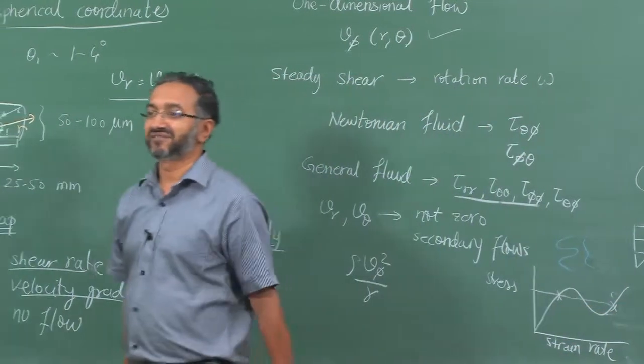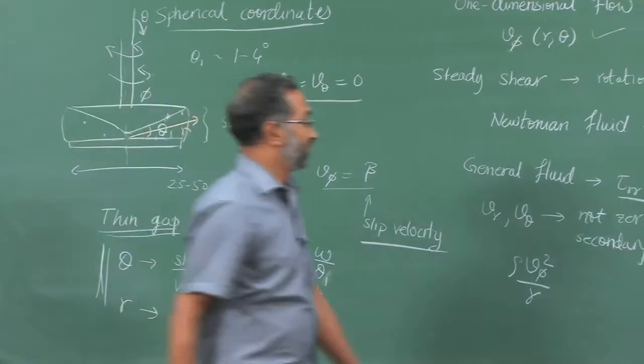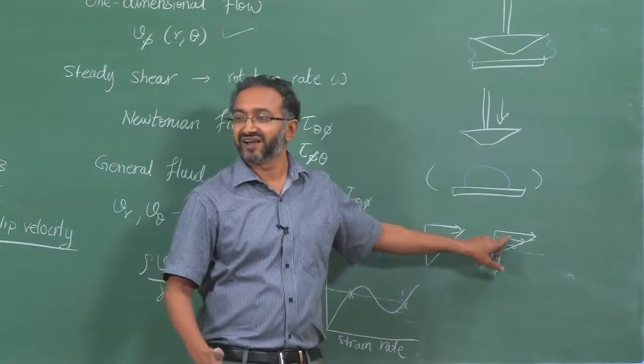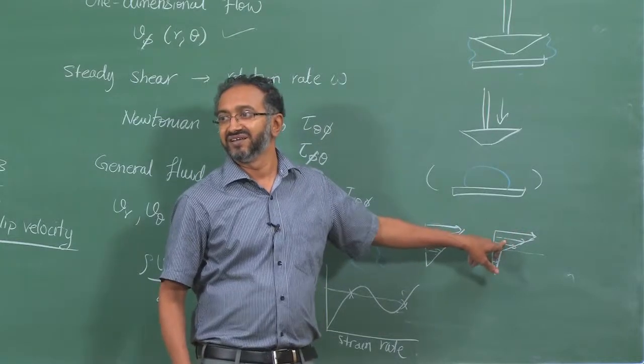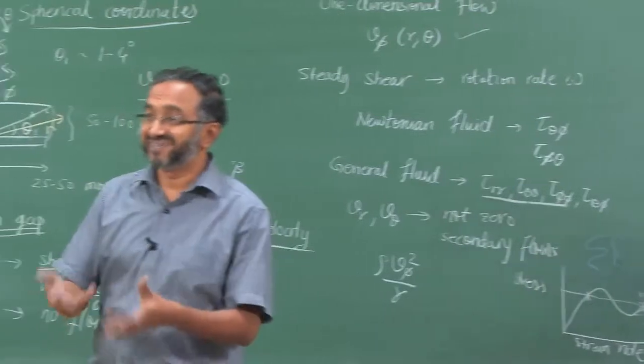In such materials there is a microstructural reason. So, in this region there is an orientation and therefore material viscosity goes down suddenly and a higher strain rate is possible. So, under some conditions you cannot prevent shear banding.